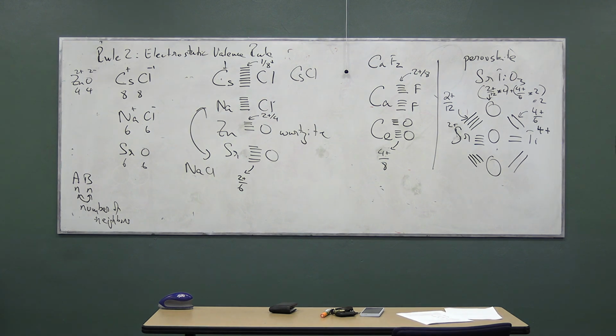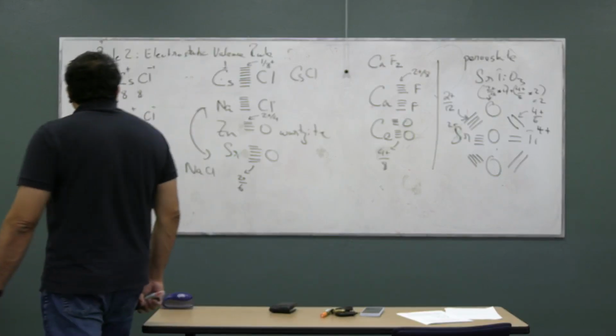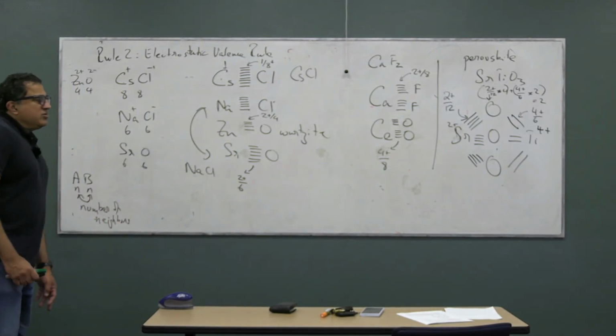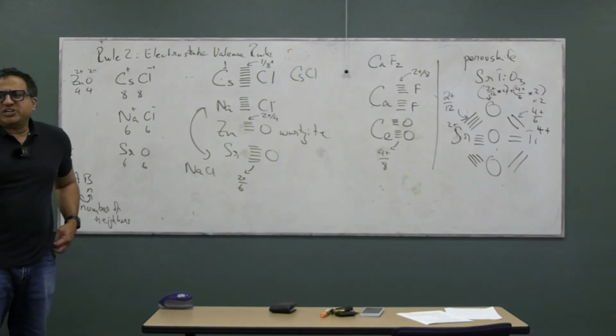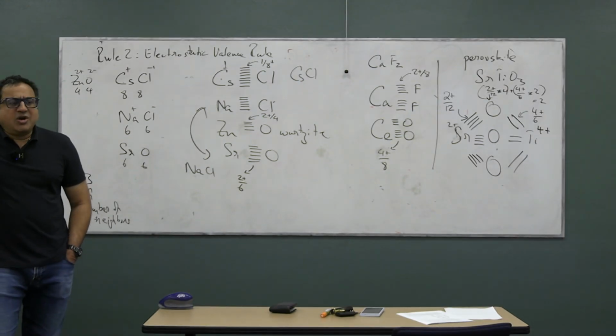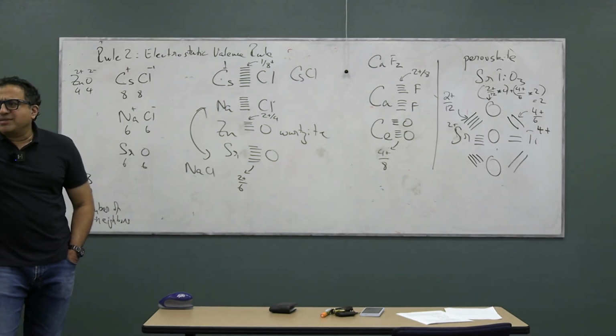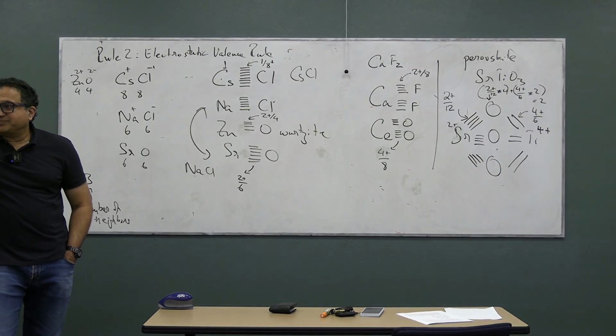So when you, however, do the electrostatic valence sums, you find that some of those oxygens don't get 2 charges, they get only 1. So there must be a hydrogen stuck to that oxygen, right? So you can use these rules quite effectively. But the nicest thing about these rules is you can very quickly check a crystal structure. Does this make sense? Or is Pauling's second rule violated? Are the charges not making sense, right?